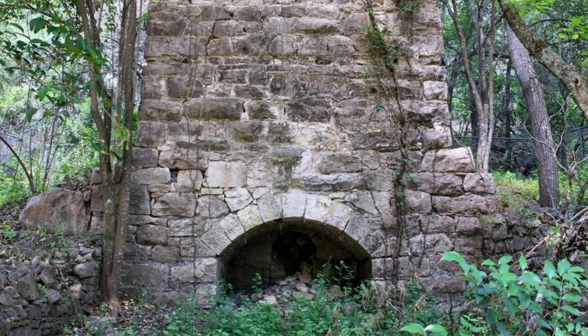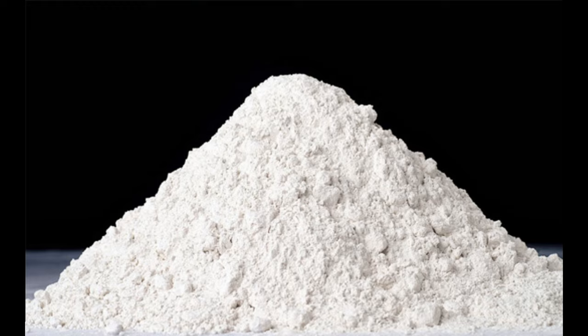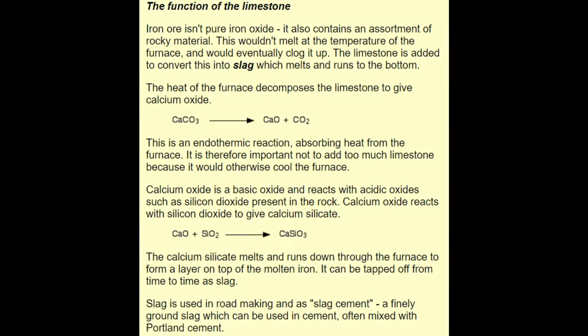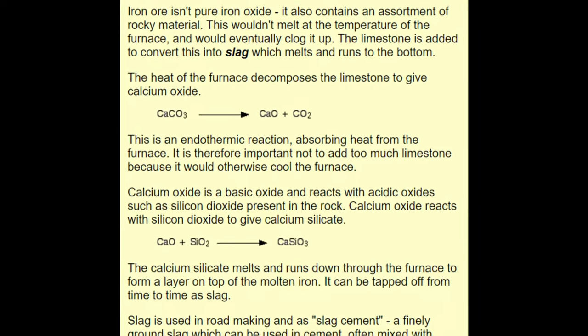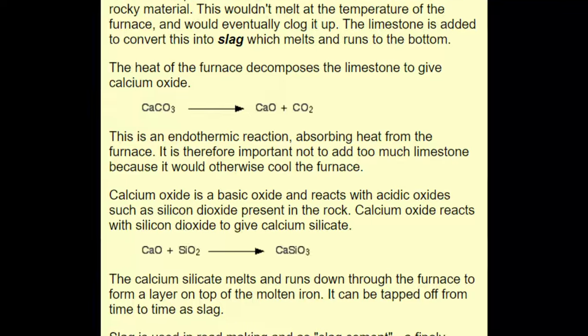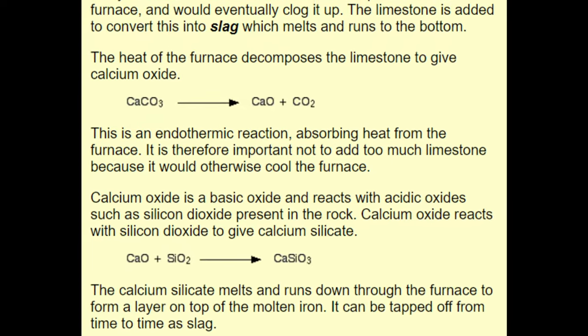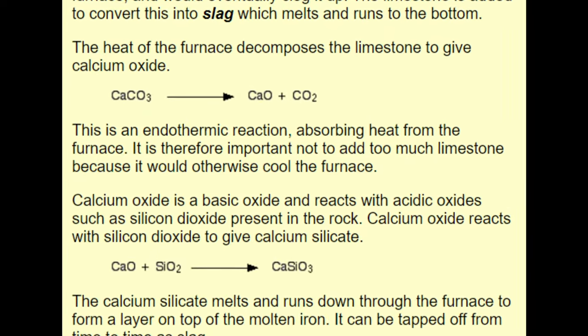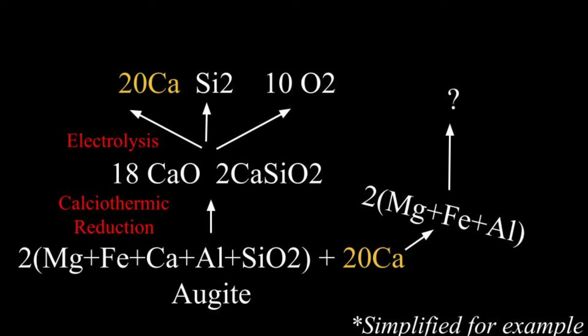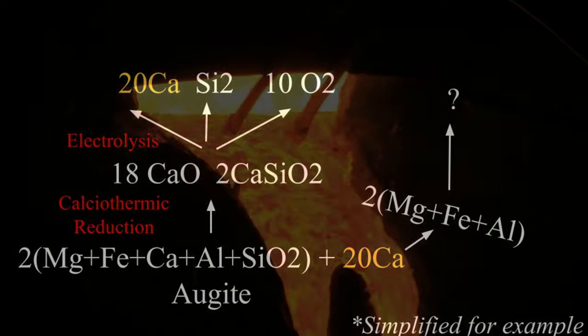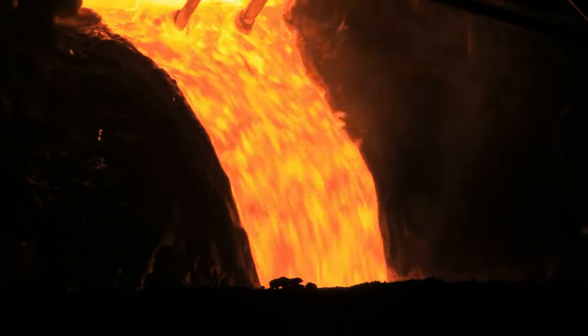And that's when it hit me. Of course, quicklime, or calcium oxide, is added to blast furnaces during iron creation to remove silicon. My answer had come in the form of a crumbling kiln built in 1860. And we are already adding calcium metal to reduce the regolith, which will form calcium oxide, which should bond with the silicon dioxide to create calcium silicate, which should slag at the top and can be removed mechanically.